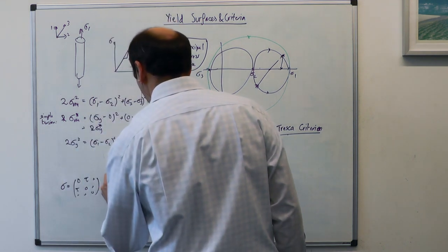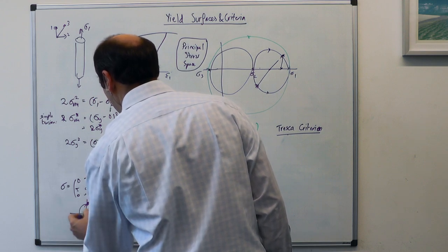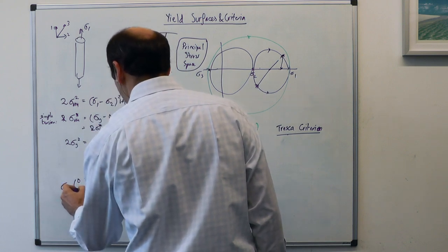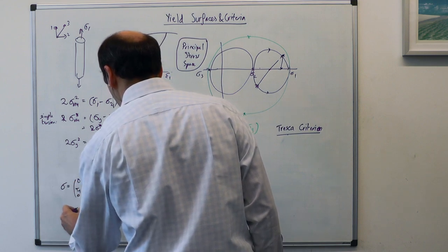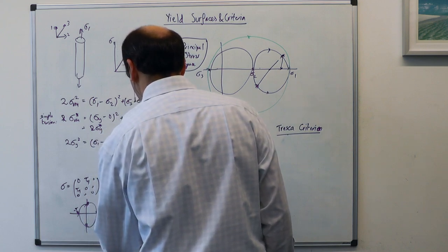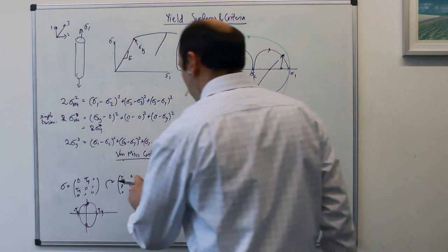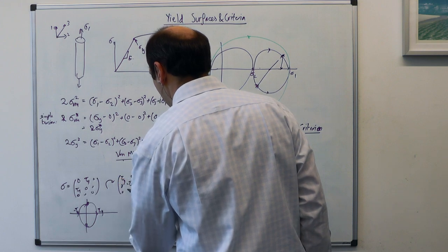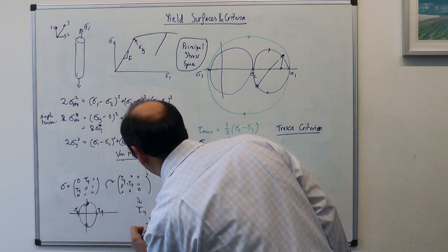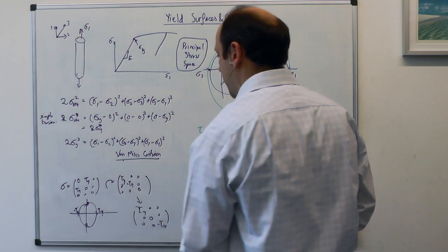If we rotate to find the principal axes, what we'll have is a Mohr's circle of this. So we'll have plus tau and minus tau. We'll call this the tau at yielding. So we'll have tau, 0, and minus tau when we order the principal stresses from biggest to smallest, when we order them from sigma 1, 2, 3. So we reorder them to be tau y, naught, minus tau y, with naught everywhere else. And so that's what's happened. Those were our principal stresses. They're tau and minus tau.